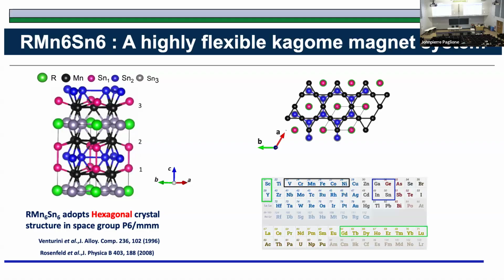What interesting behavior I found at that time is that, okay, this is great, because if I replace any of these rare earths by any of these atoms labeled here in green, you get the same structure. So you have this liberty of changing different elements and potentially tuning the properties, right? Another one is, it was more than that. You can replace this manganese with any of these 3d transition metal elements also. So there is another degree of freedom to tune the electronic as well as the magnetic properties in the system.